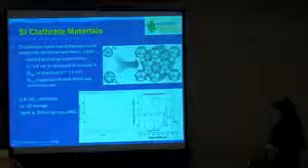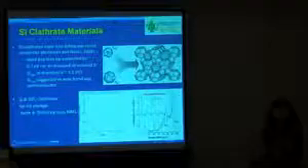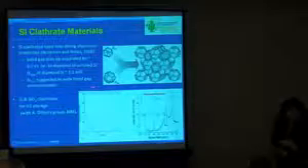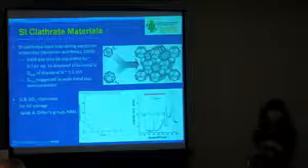And interestingly, this silica clathrate also occurs naturally. So this here is a Raman spectrum of the melanophlogite. So this is now, instead of silicon at the vertices, you have silica. And this actually occurs naturally, and the only site where it occurs has now been tarmacked in the US. But you can actually make them in the laboratory as well.